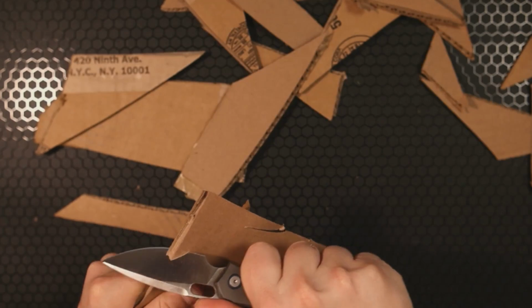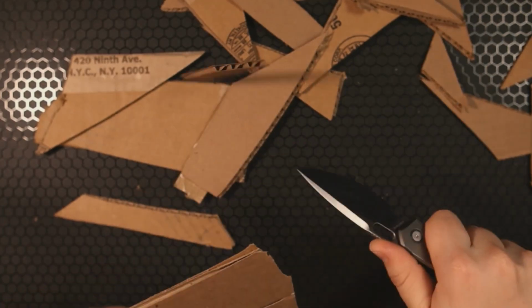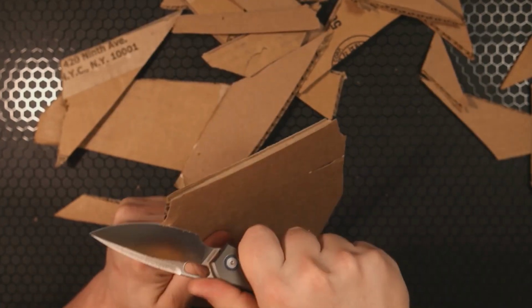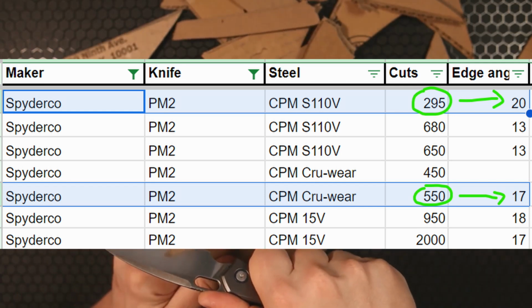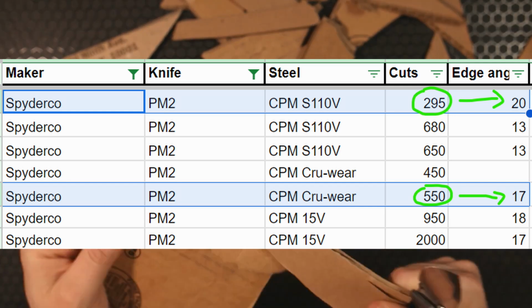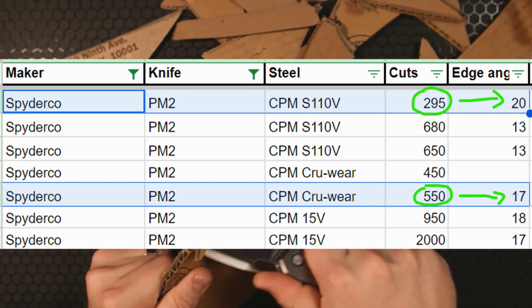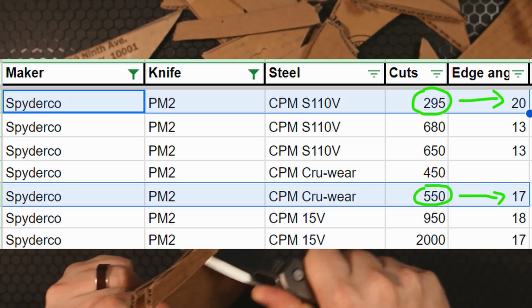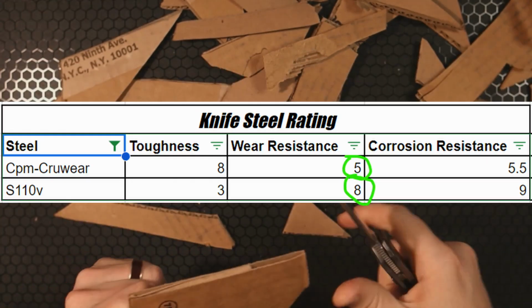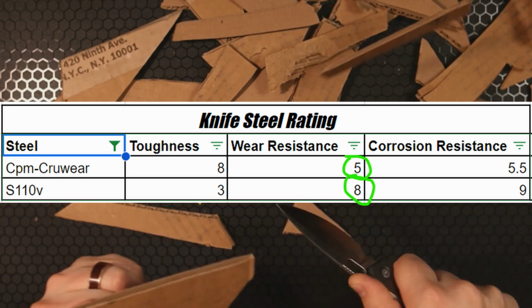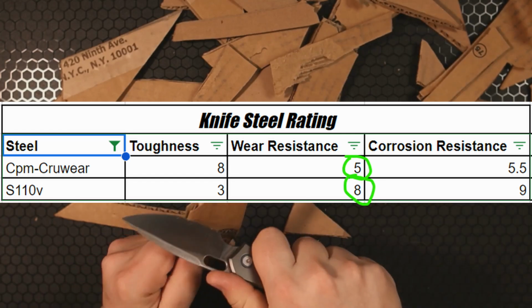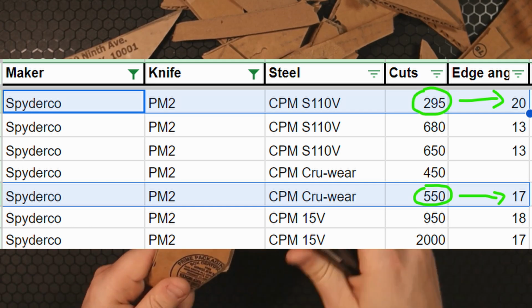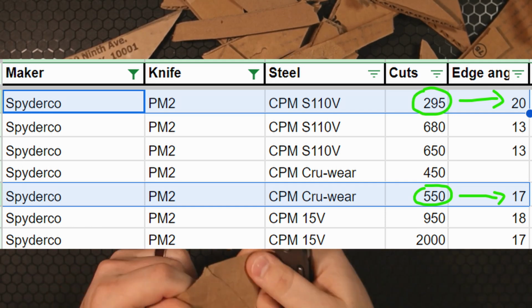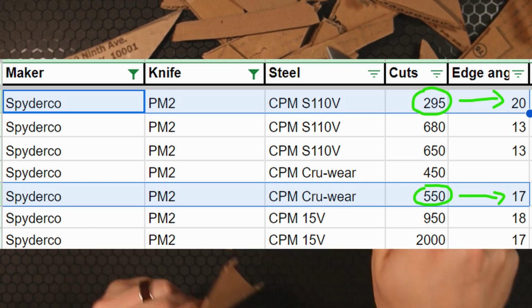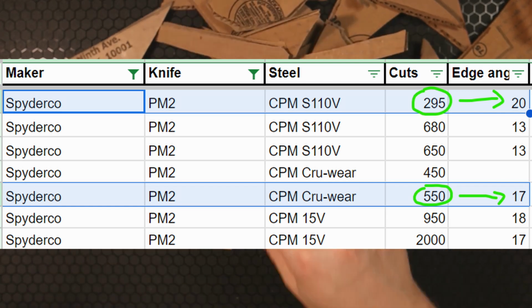For example, according to cut tests done on Cecil rope by Cedric and Ada using two different Spyderco Paramilitary 2s, one with S110V sharpened to 20 degrees and the other with CruWear sharpened to 17 degrees, they found that while S110V has much higher wear resistance than CruWear, being rated at an 8 while CruWear is only rated at a 5, the Paramilitary 2 in CruWear that had a lower edge angle of 17 degrees vastly outperformed the S110V by achieving 550 cuts.